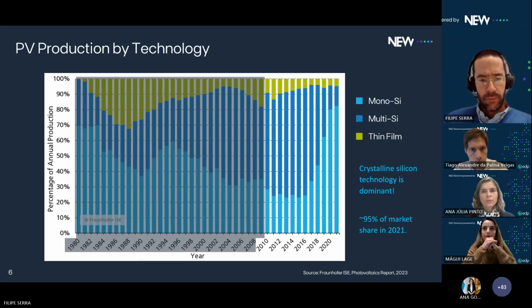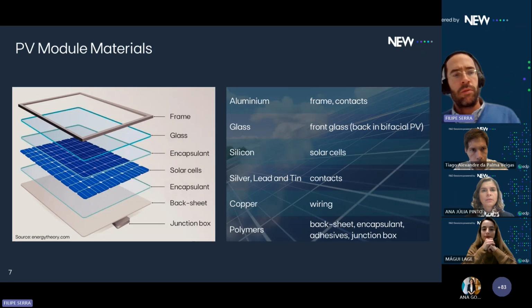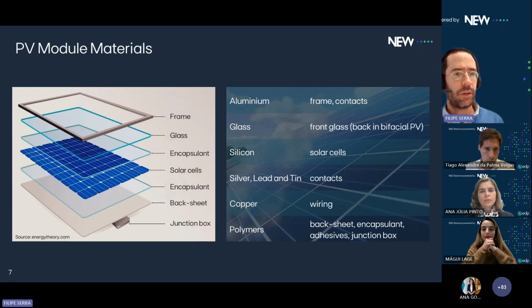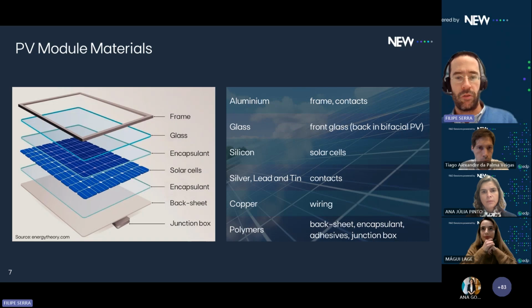And now, what are the materials that constitute a PV module? We have aluminum for the frame and the contacts. We have glass, a front glass or a back glass in the newer bifacial PV modules. We also have the silicon of the solar cells. We have silver, lead, and tin for the contacts. We have copper for wiring, and we have a set of polymers for the back sheets, for the encapsulants and the adhesives, and also the junction boxes. So all these materials need to be recycled and enter the value chain again.